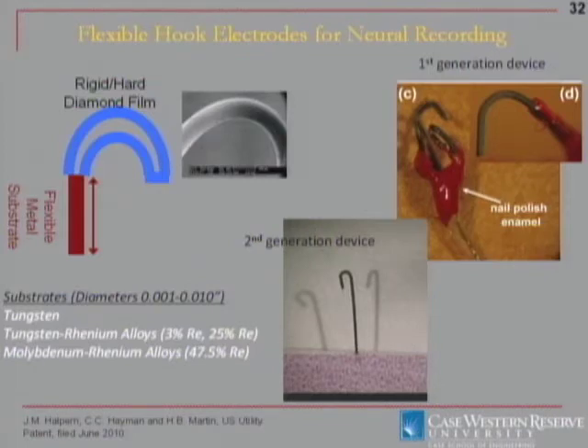So we found a set of alloys that are alloyed with rhenium, which doesn't form much of a carbide. And we were able to grow diamond that would have the substrate remain more ductile. And the structure we are looking at is a hook electrode. This is for a project we're doing with Hillel Cheel in biology for wrapping electrodes around a nerve for electrical recording. And we preformed the hook because we're not trying to make the diamond film flexible. We're just trying to make the lead stay flexible so it doesn't break off. And so we're trying to replace the very cumbersome idea of taking a diamond electrode, breaking it off, putting a metal wire and gluing it together, globbing on some epoxy or something to make it work.